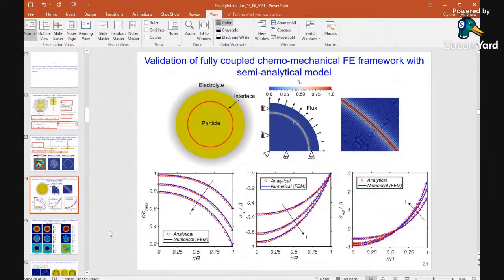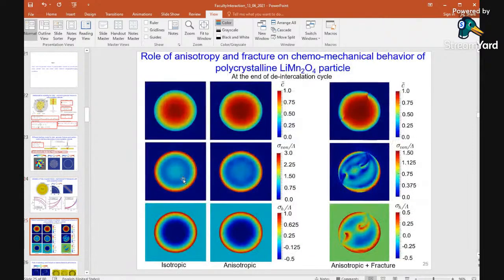Considering this diffused interface, first we validated our model, because we have to see whether the ionic transport is happening through this diffuse interface or not. So we compared our result with the available analytical solution for the concentration and the mechanical stress. We saw that it matches completely, and then we investigate that same polycrystalline structure, to see what is happening if we de-intercalate the lithium ion. The next slide will go for that.